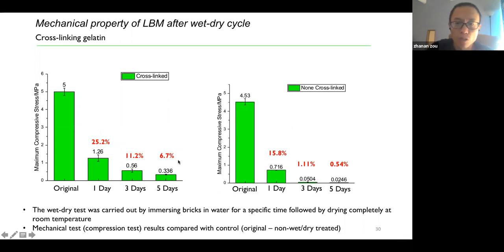And compared to the cross-linked one, if you look at the right side, which is the non-cross-linked one, after 1 day, it only retains less than 16% of mechanical stress, not to mention the 3rd day and the 5 days. So this test is to prove that the cross-linker in the system will enhance its stability, so that it will improve this mechanical property instead of changing the hydrophilicity or hydrophobicity of the brick.